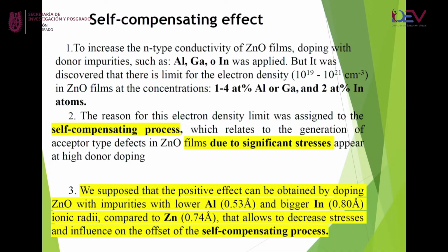Before I continue, I would like to say that in semiconductor materials, there is a self-compensation effect. This self-compensation effect is connected with the self-generation of defects when the concentration of impurity, which is especially introduced in the material, is very high. This is connected with higher tension of the material due to the difference in ionic radii of the material matrix and the material dopant introduced in the matrix.